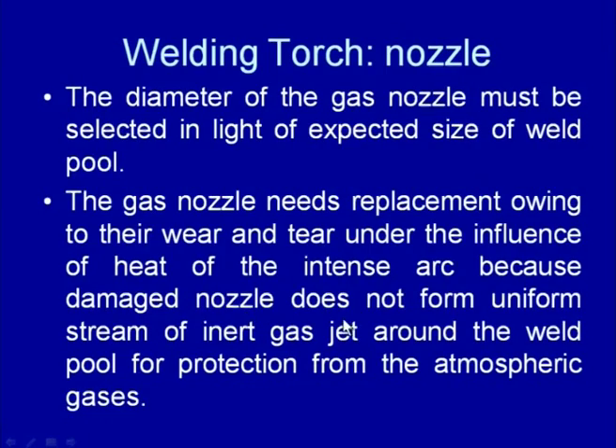Because of the damage to the nozzle by the heat of the arc, it is necessary that the damaged nozzle is replaced frequently and at regular intervals, because a damaged nozzle does not form a uniform stream of inert gas jet around the weld pool for protection from the atmospheric gases. So, the gas nozzle must be replaced regularly, because it loses its shape under the influence of the heat, and once it loses its shape, it will not be able to form a sound and effective jet around the arc, and that is why the nozzle must be replaced at regular intervals.